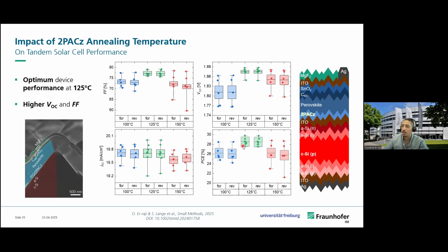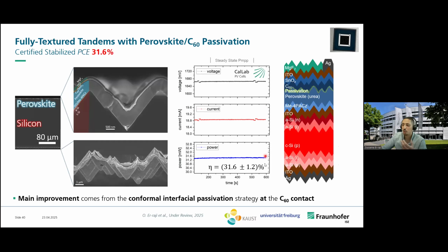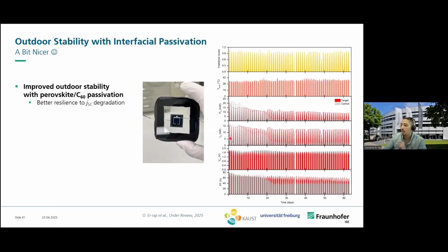So in terms of efficiency, we actually observed that the proposed interface passivation allowed us to further raise the efficiency of the cell up to a stabilized 31.6%. But more importantly, in terms of the stability, here again, you can see in dark the control device. We started to see in red for the target device a better resilience towards JSC degradation, a similar pattern in VOC, again better resilience towards fill factor degradation, and as a result, the lifetime of the cell was a bit more extended.